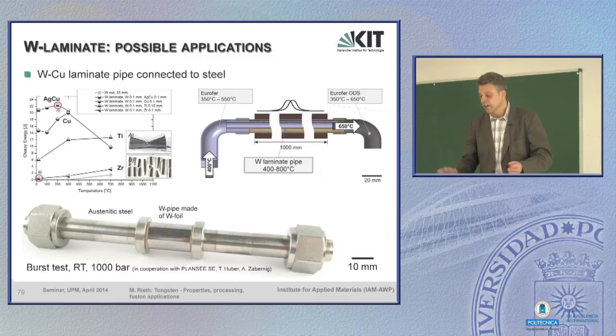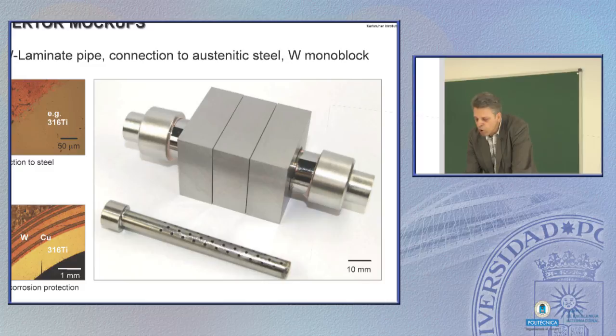With that, an idea arose that we can maybe produce larger pipes and stick some armour parts on them. To test that in general, we have performed such tests with a 100 megapascal pressure test. The foil survived, no problem. Then these are also some studies and ideas, small mock-ups, where you can see a pipe inside. This is a tungsten laminate pipe, then a tungsten monoblock as armour parts surrounding it. And inside we also use a pipe with holes in it to facilitate this jet cooling, as we have seen in the finger design.